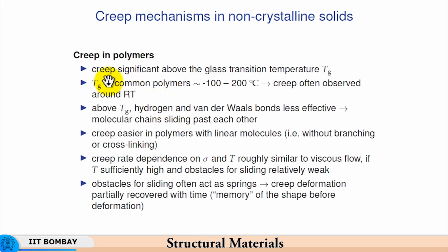So, now we have creep in polymers also. The creep is significant above the glass transition temperature, and that is when the polymer tends to behave more like glass, and Tg of common polymers is -100 to 200 degrees centigrade, and so creep is often observed even at room temperature, but then at 100 to 200 degrees centigrade it is very significant. So, above Tg, hydrogen and van der Waals bonding is less effective. Molecular chains can slide past each other.